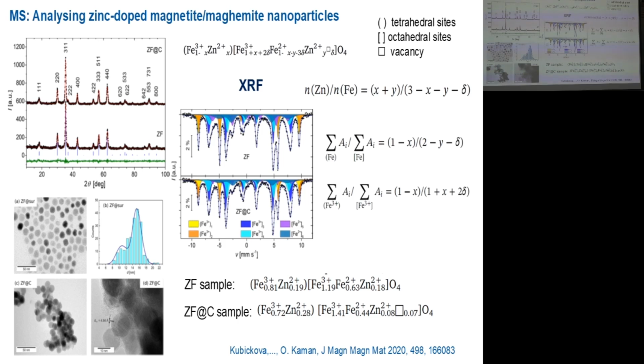So this is just to show the power of Mössbauer spectroscopy, and again I will repeat, you cannot claim anything about the identity of your iron oxides. You cannot claim anything about the oxygen stoichiometry, if it is Fe3O4, Fe2O3, or some mixture in between, without such analysis.